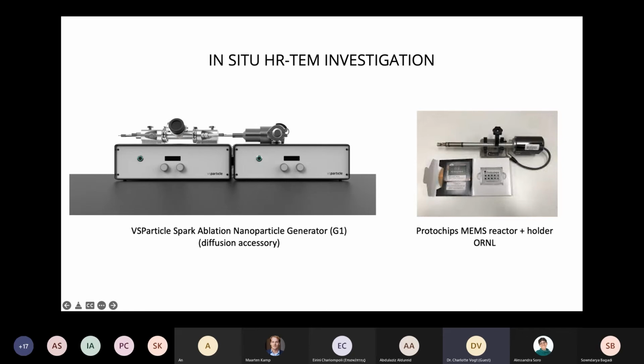We went to Oak Ridge National Laboratory, and we prepared samples on those silicon nitride MEMS reactors, using the spark ablation nanoparticle generator, the G1. And we used for this the diffusion accessory, because these silicon nitride windows are very brittle. If you're using, for example, size selection with the spark ablation nanoparticle generator, we still have the problem of breaking these. But of course, you get high resolution with in situ TEM, so we can focus even on different nanoparticle sizes using this diffusion accessory.